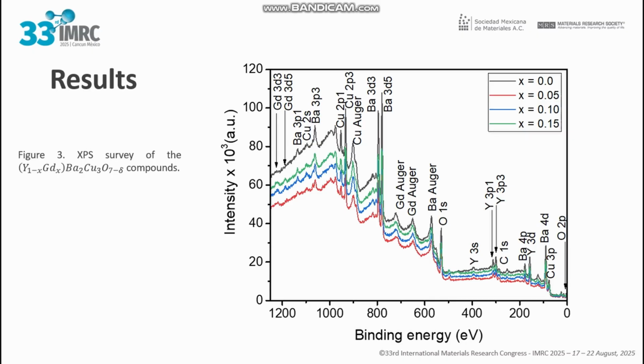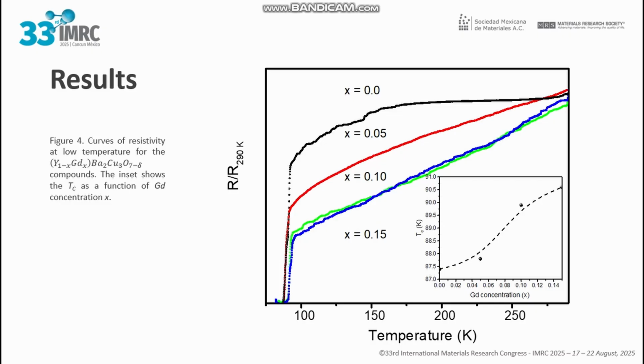Next, we have the XPS survey of the yttrium barium copper oxide doped with gadolinium compounds. Here we can see that we successfully identified the chemical states for each element, as well as the Auger peaks. And lastly, here we have a graph that shows the curves of resistivity at low temperatures for the compounds synthesized. The inset of this graph shows that the Tc of each compound increased slightly as a function of the gadolinium content. We can also see that all of the compounds showed a true transition into the superconducting state near a critical temperature of around 90 Kelvin.